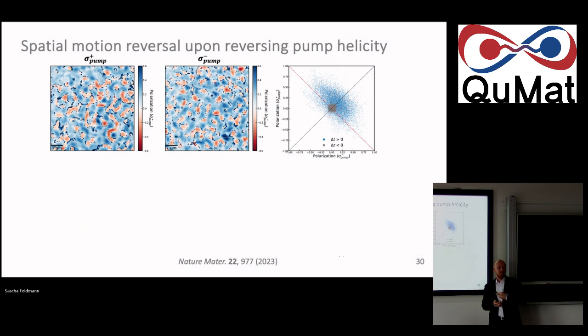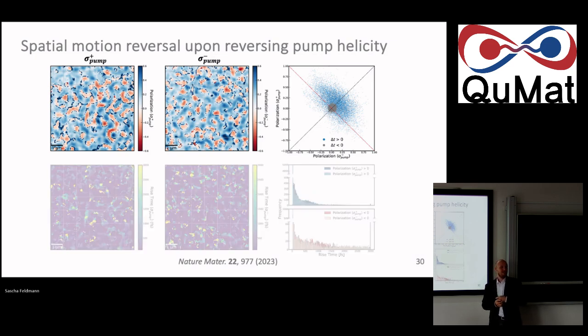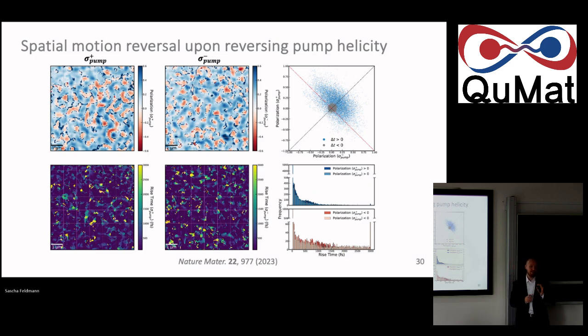What's even more in my face kind of supporting this, which is when I really started to believe it, is the kinetics. Now you can say, okay, you are still not good with your polarization optics, no matter how good you tried. This is just an intensity set. But all the kinetics that were previously associated, say, with the positive domain to be prompt are now negative domains, and they are also delayed. So this whole kinetic has also changed now. And that is not something you can explain by having been a little bit off with your polarization intensity. So the fact that all the kinetics changed as well really hinted at this being very much not an artifact.